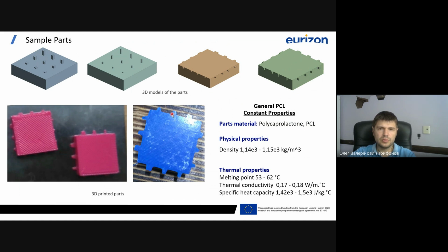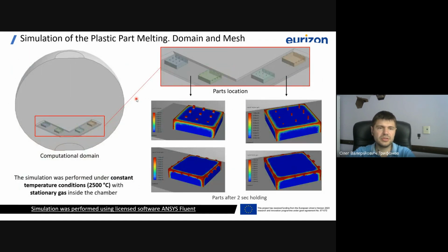Another assumption was constant temperature conditions inside the chamber. So we assume that initially we have a temperature which corresponds to the combustion products after the combustion, but the distribution inside was uniform, and we don't take into account flows and velocities inside the chamber after combustion. And very briefly, results show us that liquid formation, meaning we can observe melting of the parts, occurs exactly on the small elements and on the edges.